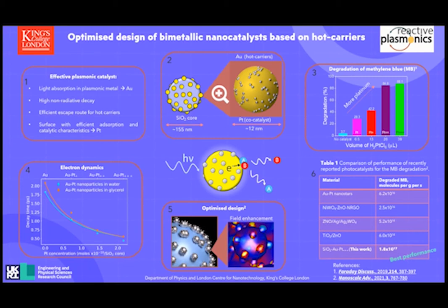Not only methylene blue, but all organic pollutants sensitive to superoxide anion species can also be degraded by the designed photocatalyst. The proposed plasmonic heterostructures are not limited to water purification from organic dyes. By engineering an appropriate plasmonic nanostructure in conjunction with the choice of a catalytic metal suitable for a given reaction, it is possible to maximize a reaction rate due to hot electron excitation and transfer.